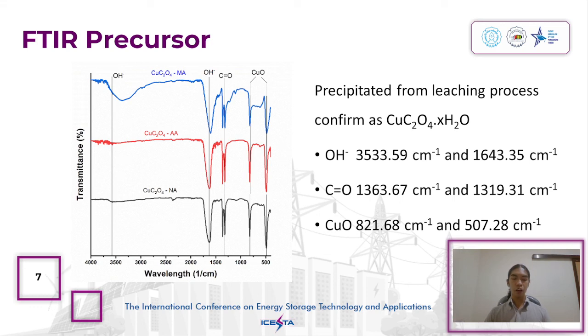In the FTIR spectra of each sample, the functional groups that can be observed are the hydroxide group, C=O group, and copper oxide bond. Hence, it can be concluded that the precipitate formed by reaction of leaching solution with oxalic acid produced copper oxalate x hydrate, where x is less than 1, which is in agreement with the XRD result.